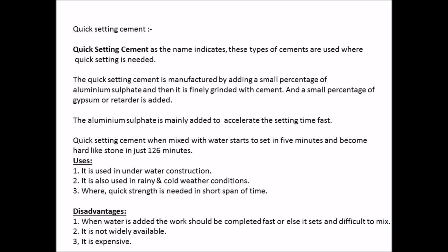The major disadvantage: the work we saw in the previous video, I will show you the clip again, cannot be done with quick setting cement. You have to be quick as light, because it will start setting in just 5 minutes. Yeah, it will start setting in 5 minutes and it will be rock hard in 126 minutes.